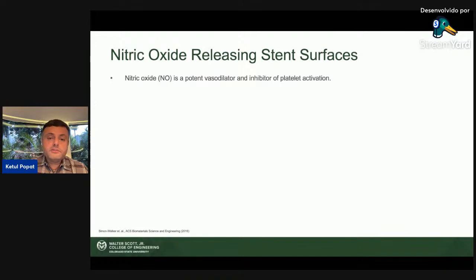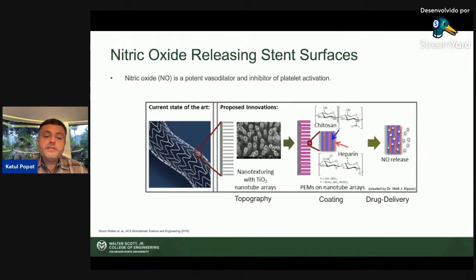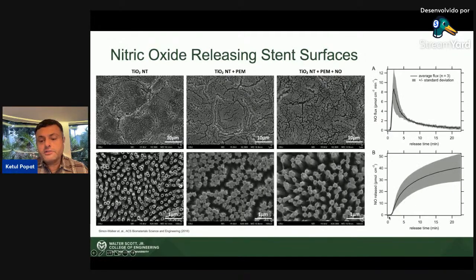The next thing that we also did is we tried to put nitric oxide on the surface. Nitric oxide is very interesting because in our blood vessel, nitric oxide is being released all the time in our blood, which also helps in preventing blood clotting. And so we developed some chemistry techniques using these polyelectrolyte multilayers where we put nitric oxide in it and slowly release it, so it actually prevents the blood clotting from happening. And so we have developed this chemistry and we've also looked at how the nitric oxide is releasing.